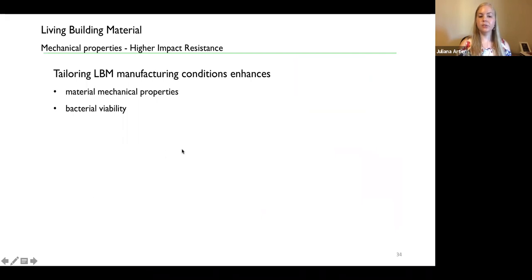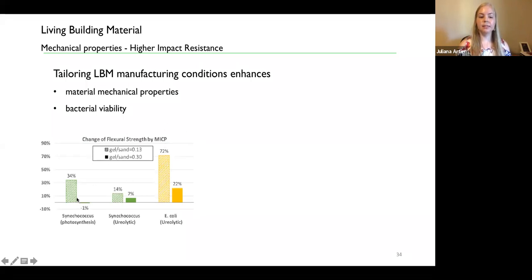So later on, we wanted to tailor these LBMs more by manufacturing the conditions, by changing amounts of gelatin being added, or changing the bacteria and the metabolic process being used. We talked a little bit about using different biopolymers, which we are still studying, and introducing different fibers into these materials. But simply by adding different bacteria through different biological processes, we saw that we could get a very increased amount of change in our flexural strength, which is related to this higher impact resistance with the MICP, both by photosynthetic or ureolytic pathways in this bacteria. And these flexural strengths were even comparable to high fiber bricks or even cement mortars, which is used for comparison for engineering purposes.